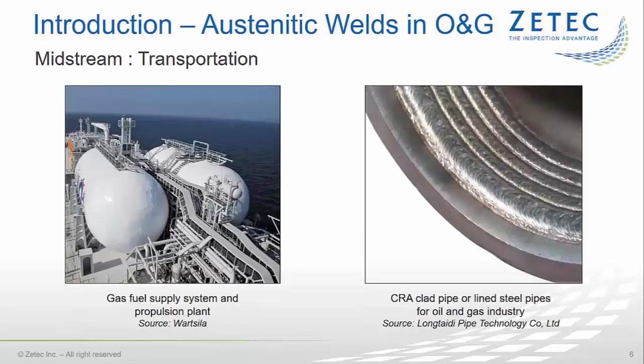For transportation activities in midstream, the use of duplex-grade steels for storage tanks allows up to 40% wall thickness reduction at equal strength, thus creating saving in welding material, transportation, and construction costs. Corrosion-resistant alloys, or CRAs, are used to clad the inside surface of steel pipe, and 9% nickel alloys are typically used for LNG tank manufacturing.